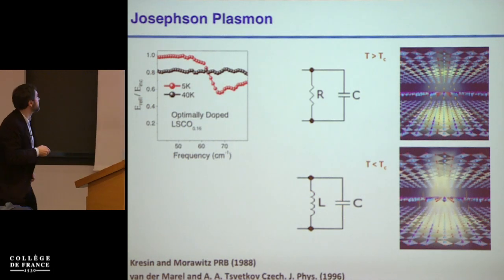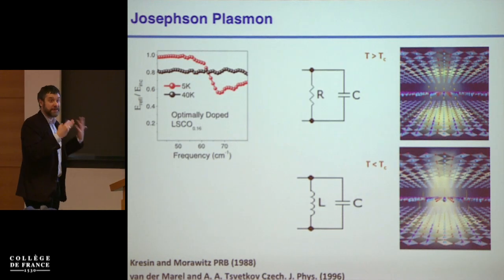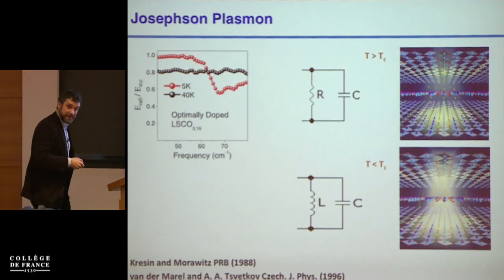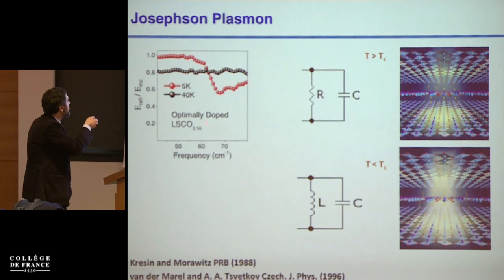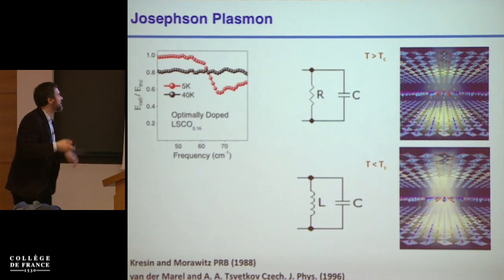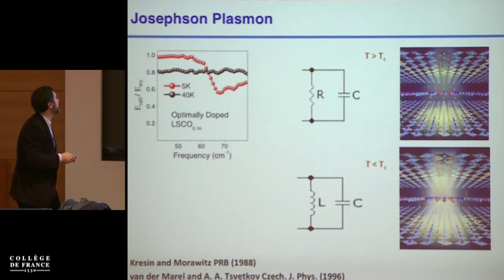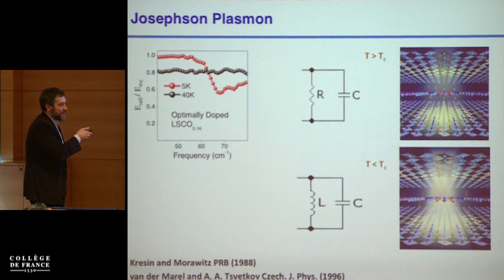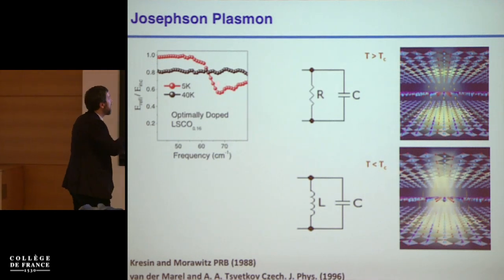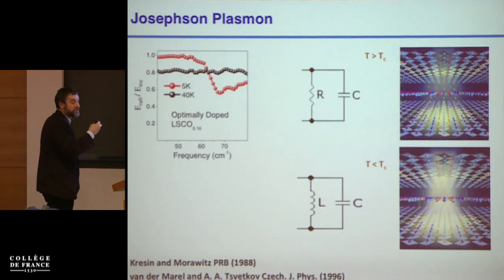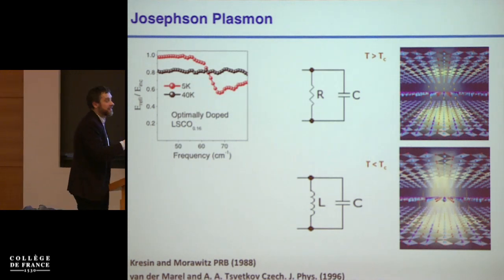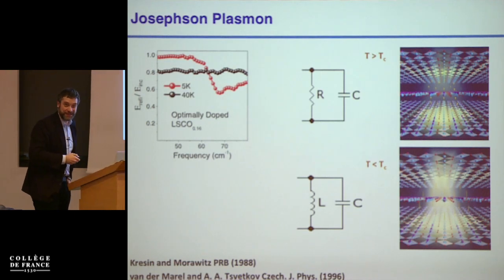Okay, so this is if I take an optimally doped lanthanum-strontium cuprate material and I cool it down at equilibrium, I go from the black flat reflectivity to the red reflectivity, which shows a plasma edge. Age is really not my friend here. Okay, with this plasma edge being at a frequency which is 1 over square root of LC, where L is related to the number of Cooper pairs.